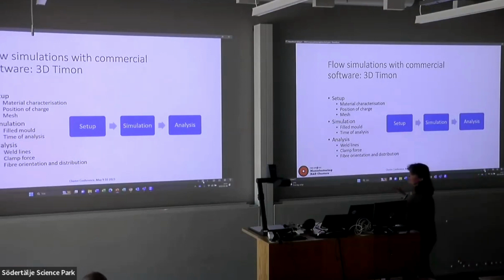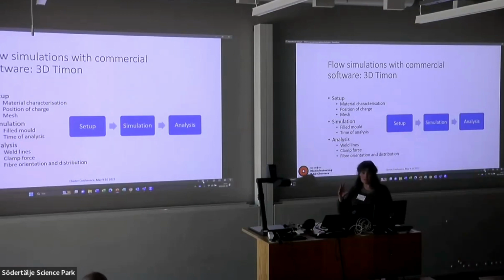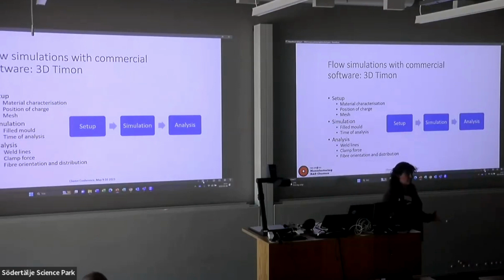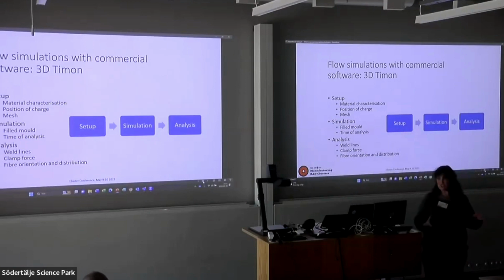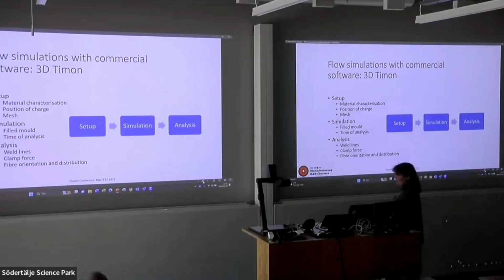The clamping force needed is another issue when we're looking at carbon fiber SMC, which is an SMC with a high amount of fibers. So it really requires quite a lot of force to start clamping together. And then, like we said, the fiber orientation and fiber distribution.